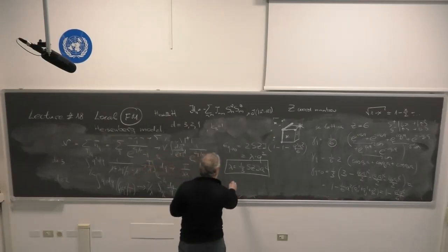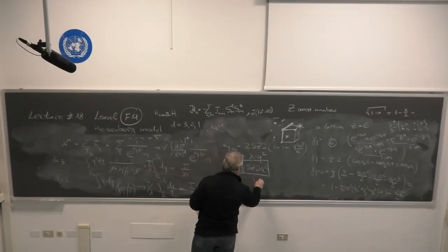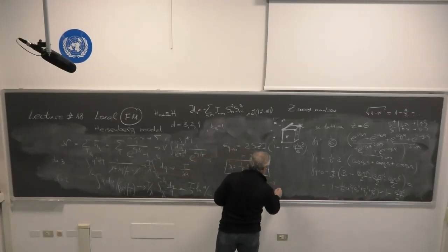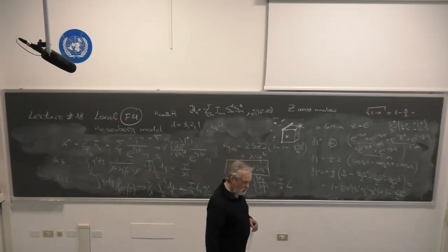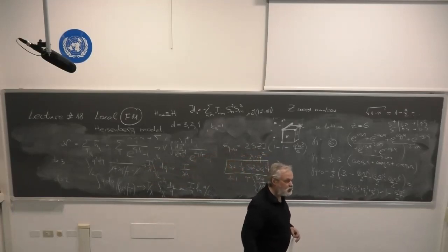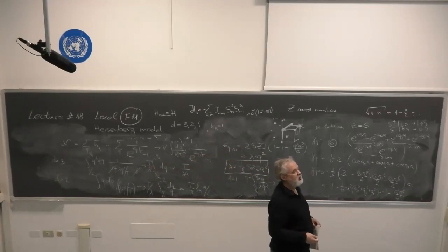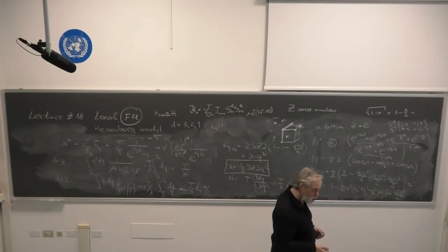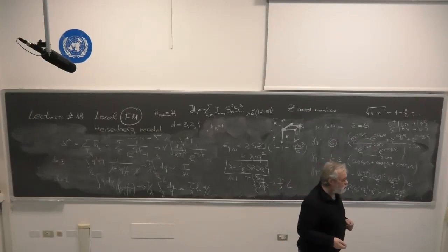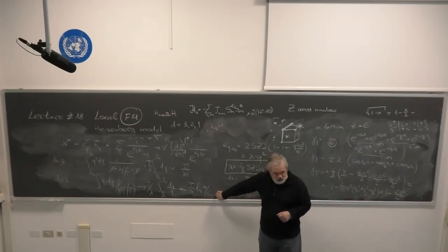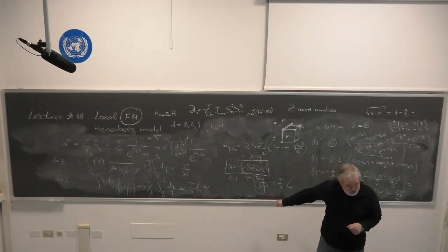And example number 3, d equal to 1, I have integral dq divided by lambda q squared from 1 over L to 1 over A times T. So this is T over lambda times system size. So the number of magnons grows with the system size. What is the conclusion from this exercise? The conclusion is that the long-range order for the system with a short-range interaction is only possible for temperature equal to 0 for 2-dimensional system and is impossible for 1-dimensional system.